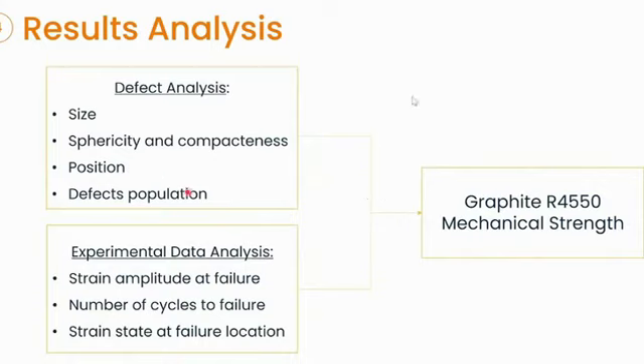And their stress intensity factor, while the ultrasound test will provide the strain amplitude at the moment of failure at the failure position with the number of cycles until failure, and this data will contribute to evaluate the graphite R4550's mechanical strength.